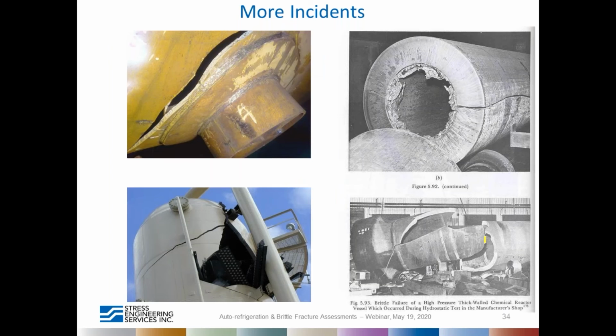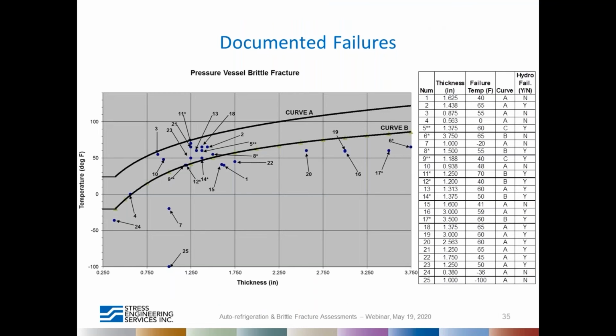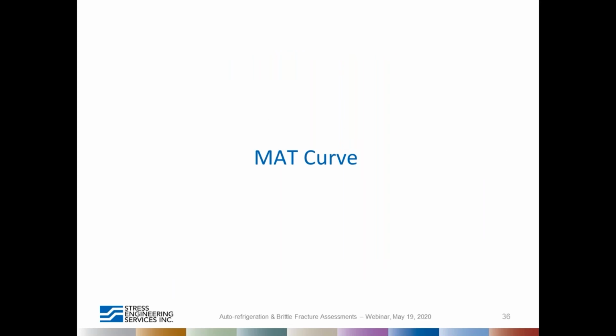More incidents. These are some of the pictures that were taken from API 571, and most of these failures were during hydrotest. The reason we bring that up is that the record of failures has been plotted here by one of our colleagues, and he looked at the data over the years and plotted it against the exemption curve and looked at which ones failed and what thicknesses have been failing. If you look at the bottom of this graph, most of the failures are at about half-inch thickness, and 2/3 of these recorded failures are during hydrotest. So basically, most of the failures that are still happening are in hydrotest.